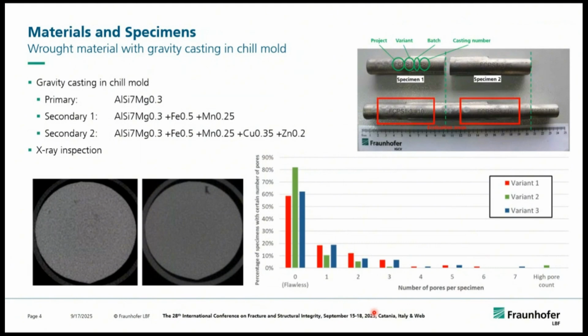For sure, we made some quality assurance. So colleagues from other Fraunhofer institutes made some scans, X-ray inspections, CT scans, to see what the implications are from the primary to those secondary alloys in terms of defect assembly and defect distribution. What we got to know at the end from those results: most of those situations and materials were flawless and the components were comparably sound, and we could not really see that from the secondary alloy, those effects of iron or manganese will add an additional factor of defects in the microstructure, which is good, and was the first proof for us that it can work to use recycling aluminium.